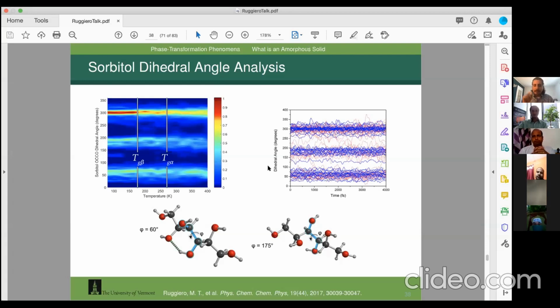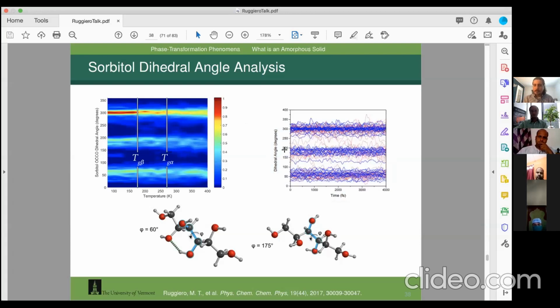What we found was if we tracked every dihedral angle in this amorphous sorbitol simulation above the glass transition, so at 300 Kelvin or 350 Kelvin, these are the red lines in this figure. What you see is that the molecules jump between these well-defined regions. There are three well-defined regions, and at high temperatures some of the dihedral angles are jumping between regions. Whereas at low temperatures, below TG beta, for example here, the dihedral angle just oscillates around and stays in one place.